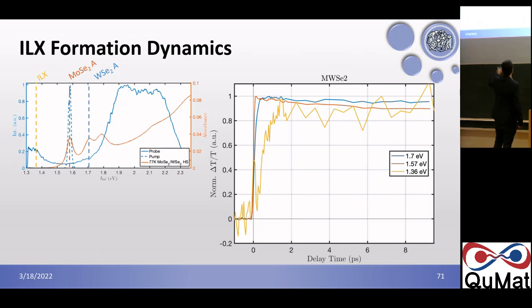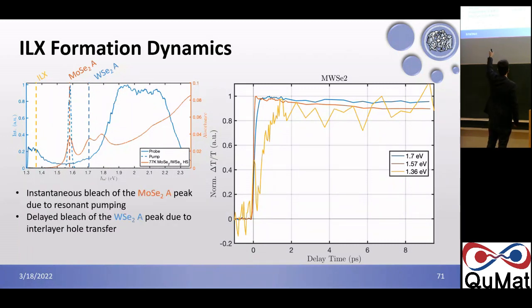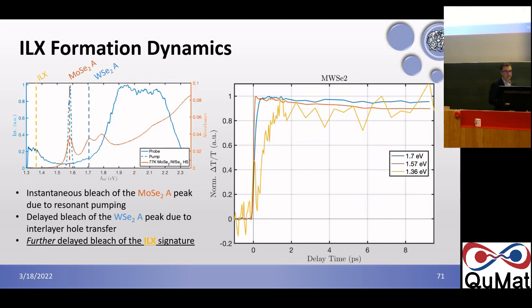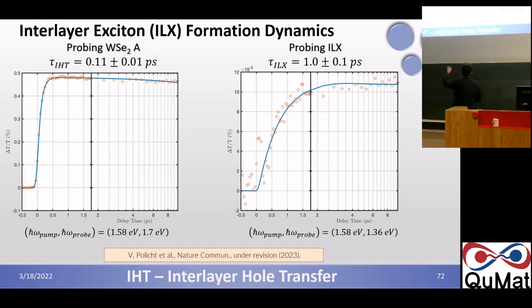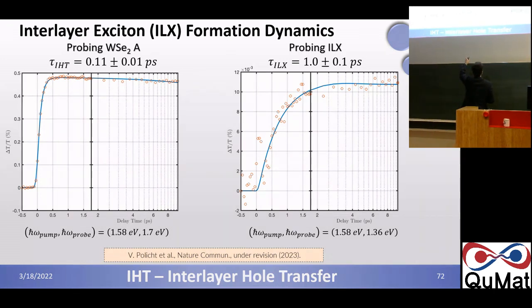And now we can look at the dynamics, and we see that the interlayer exciton is formed with a time constant of the order of 1 picosecond. You see that the MoSe2 A peak is bleaching instantaneously. The WSe2 A peak is bleaching with a delay of approximately 100 femtoseconds. You can see it clearly, there is a delay, but a small delay. But this interlayer exciton is very weak, and it has a delay on the order of 2 picoseconds almost. So the signature of the interlayer exciton is further delayed. And here we can make a fit. This is actually published, so I can say you see the rise time of the interlayer exciton, you can fit it to something on the order of 1